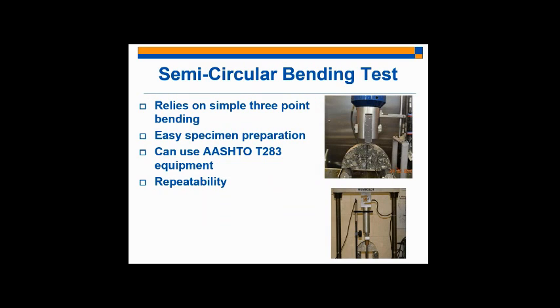And so, having said this, I present to you the semicircular bending test. Mostly everyone's probably heard about this test. This is basically a very simple three-point bending test. It's a fracture test, right? The specimens are produced from the Superpave gyratory compaction cylinders. You compact your cylinder in the Superpave gyratory compactor. You remove the top and bottom portions of the cylinder, or the pill, and then extract two 50-millimeter thick slices from the center of the pill, halve them, and notch the base of each half. That results in the SCB, the semicircular bending beam test, which you can see in the figure at the top right. So it's a very simple test specimen fabrication process.